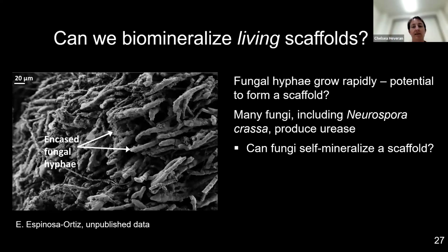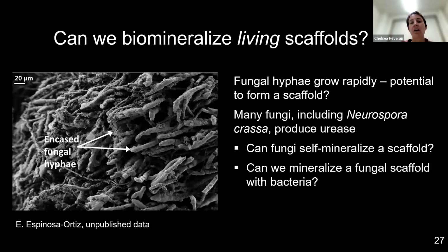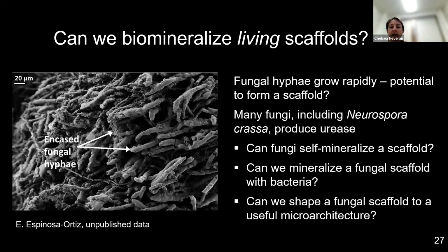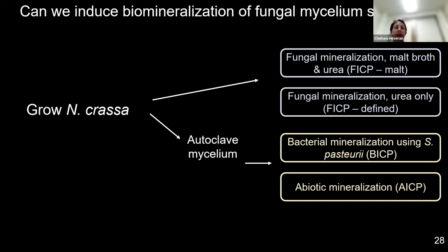We wanted to know if that could be something that a living scaffold is capable of, or if it could support the biomineralization by bacteria, or if we could shape this scaffold to be a useful microarchitecture. So we performed an experiment where we grew up N. crassa, and then we had 4 conditions. Two of our conditions, we kept the fungal mycelium alive, and we fed it different things. The first was a rich nutrient source, and the second was a defined nutrient source, but the organism is forced to do urea hydrolysis. So we thought that would probably lead to greater precipitation of calcium carbonate because this microorganism has very diverse metabolism. We also did another condition where we would kill the mycelium and then we would grow up ureolytic microbes such as Sporosarcina pasteurii on this mycelium, and then we had an abiotic mineralization control.